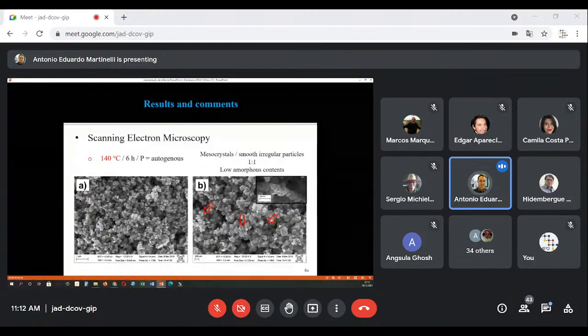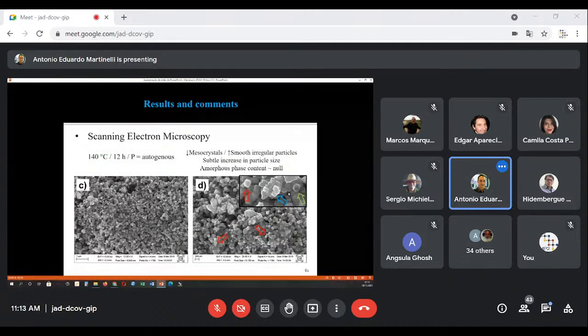At 140 degrees C, 6 hours, autogenous pressure, we have a 1-to-1 ratio between mesocrystals and smooth irregular particles and low amorphous content because we are at higher temperatures. So the kinetics of the formation, here we have a very nice sequence of mesocrystals shown to you. And this scale here is 200 nanometers. 140 degrees, 12 hours, autogenous pressure. Now we have the growth of irregular particles at the expense of the former mesocrystals, and a subtle increase in particle size. And the content of amorphous phase now is virtually null.